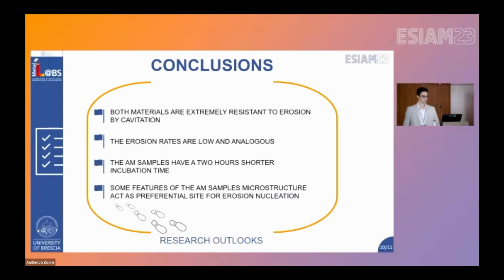So to summarize, the aim of this work was to evaluate the erosion resistance of these additive maraging steels, and we used forged one as a reference. Both the materials were extremely resistant to cavitation erosion. The erosion rates were low and almost analogous. The main difference was the earlier incubation time of the additive sample, by 2 hours. But in the end, after 24 hours, the difference in the mass loss was just 3 milligrams.